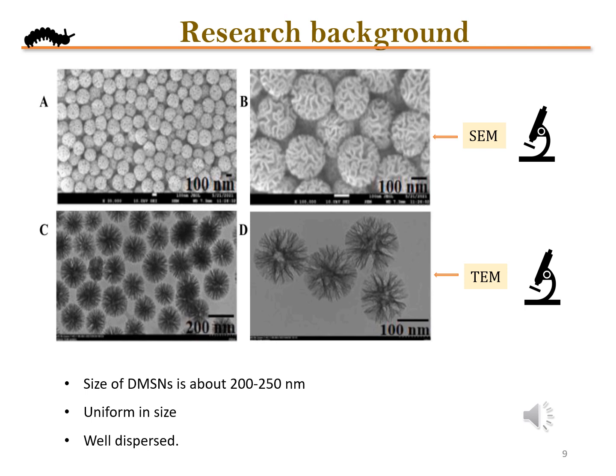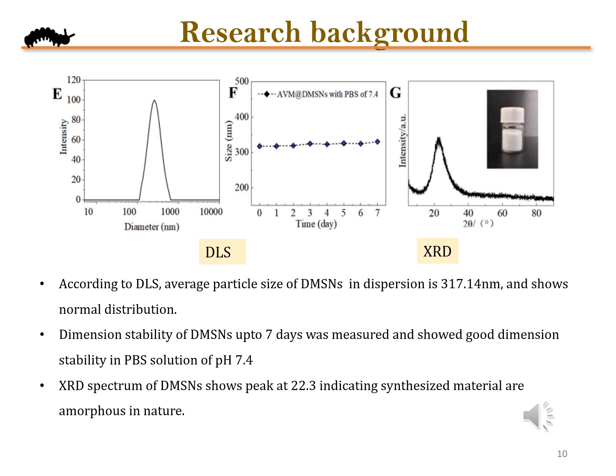From the results, we came to know the size of DMSNs is about 200 to 250 nanometers, and they are uniform in size and well dispersed. Later, DLS analysis was performed to know the average particle size of DMSNs, which was about 317.14 nanometers in dispersion and also shows a normal distribution. The stability of the dimensions of DMSNs was also measured up to 7 days, and they were found stable in a solution of pH 7.4.